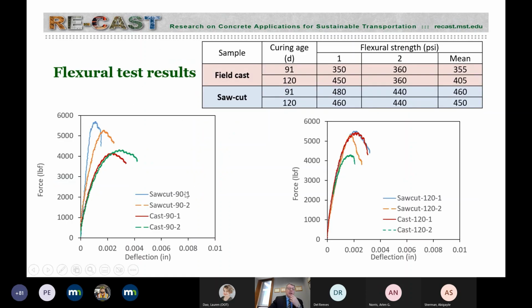And here we are plotting the force versus deflection to determine the flexure strengths of two prisms. And you can see that the saw-cut ones are those two on top at 90 days. And then at 120 days, we have those also on top, the blue and the orange. And at 90 days, the samples that were taken from the field and consolidated properly were slightly lower. So all in all, there's not a lot of spread between the in situ and field prepared samples.